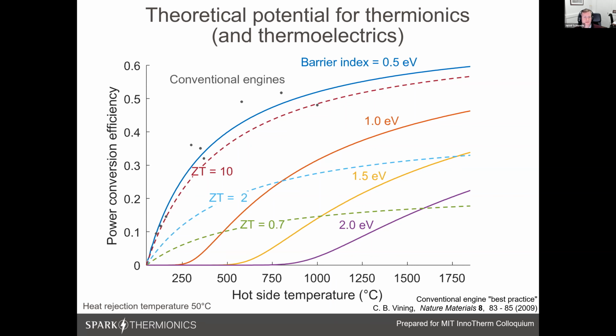So what I want to emphasize here is, while it's very challenging to integrate these low work function materials, it's not at all crazy to be talking about a barrier index of half a volt to a volt. And in fact, we've demonstrated work functions as low as 0.6 eV. This would be, if you're familiar with thermoelectrics, competitive with a ZT of 10. It really shows the opportunity for reducing work function and reducing this voltage that we have to apply within the gap.